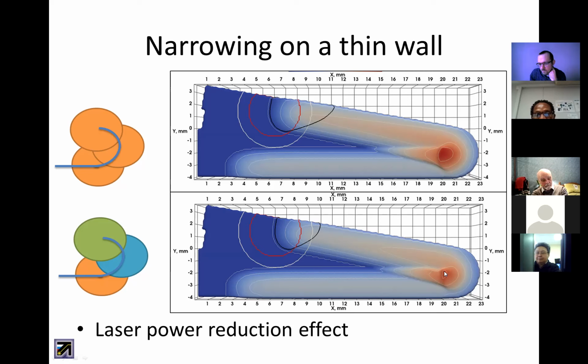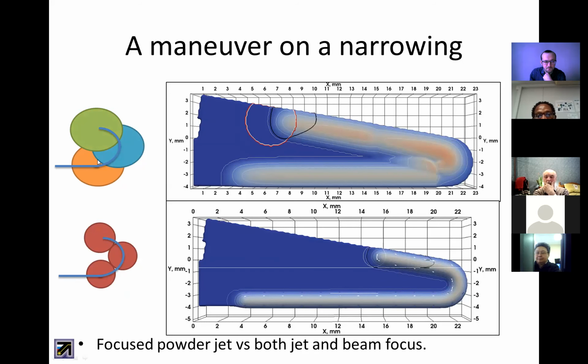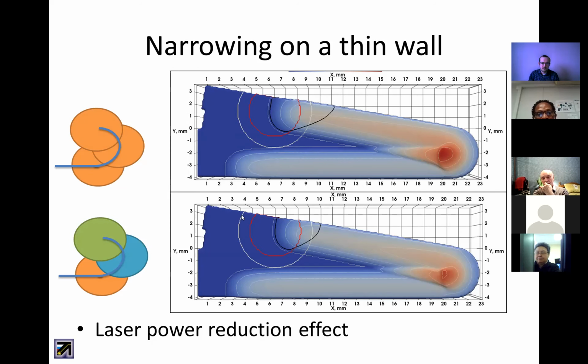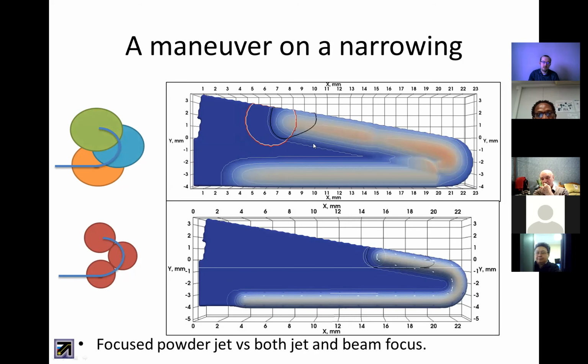Only a small improvement is seen here, because the additional powder is still caught by the narrowing, even if we preserve the melt pool parameters. After that, we show that we can get mostly defectless narrowing by using a focused powder beam. You can see by the white circle a powder jet, which is larger than the laser beam, but if we focus it to the same dimensions as the laser beam, we can have almost defectless narrowing.